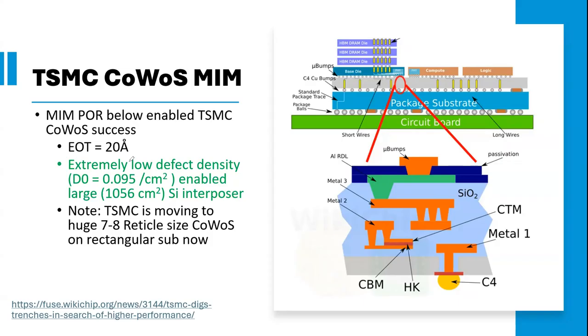Reasonably good. It does not really matter. It serves their purpose. But I think the one outstanding thing is the extremely low defect density. D-naught is 0.095. This is much lower than reported on the actual die. I mean, the actual die is like, I'll show you later, 0.8, less than 1. But 0.09, this is really good. And this low defect density enables their large silicon interposer. I think that's the key.